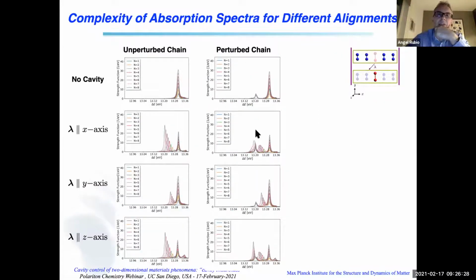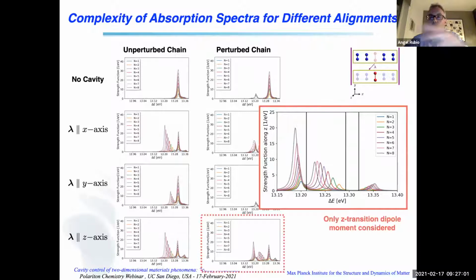Okay, this is the figure that you don't see, and you don't need to see it, because the only thing that you want to get from this is, in the case of no cavity, for the unperturbed chain or the perturbed chain, you see that you have a main peak with the intensity increasing with the number of dimers which are not overlapping. And something I wanted to give your attention to is that once you perturb one of the molecules, there is a new peak appearing, which is the defect peak, and that peak is separated from the main peak. Okay, and now the question is, what happens if I couple that configuration, which is without the cavity, now with the cavity? And that's what I wanted you to go through. Then you get the main peak, which is the excitation of this N=2 dimer in the cavity.